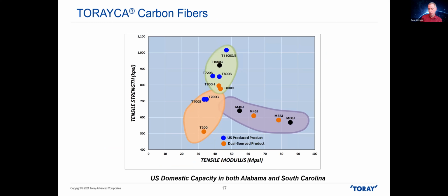If you look at that lobe that's on the lower left, those are standard modulus fibers, and the implication there is they're the lower stiffness group, but they actually still have stiffnesses that approximate, actually higher than steel, and they have strengths that are on the order of 2 to 3 times that of high tensile steel. If you look at the top center lobe, those fibers have 1 to 1.5 or slightly more times the stiffness of steel, and they have 5 times the strength of high tensile steel. And the lobe on the right there has stiffnesses up to and over 3 times that of steel, and strengths that are up to 3 times that of high tensile steel.